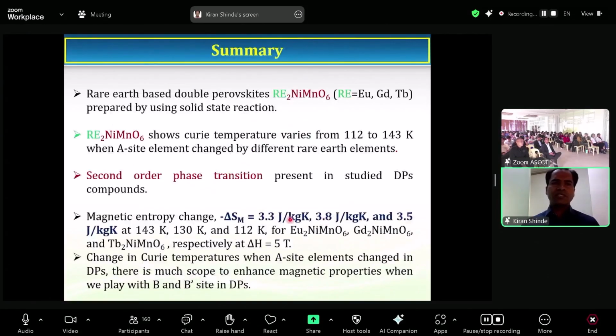So here are some conclusions of this double perovskite material. Using the solid state reaction, we developed this rare earth-based double perovskite, and we found a change in the Curie temperature from 112 Kelvin to 143 Kelvin when we replaced the A site element. Then we confirmed that this compound shows a second order phase transition, and we found that the magnetic entropy change is 3.3, 3.8 and 3.5, which are nearly equal, but the Curie temperature shows a drastic change in the materials.